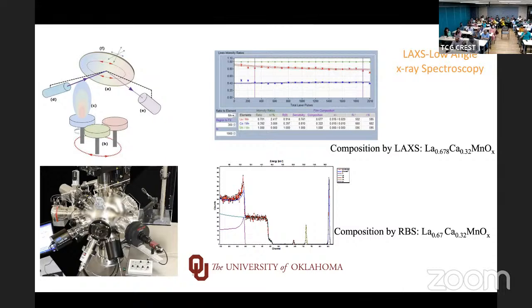Whereas, I send the film to a company outside who do Rutherford backscattering. It's considered kind of a standard for composition measurement, and this data comes back to us after 3 weeks. Look at the composition numbers, 0.67, 0.32. To within 1%, we are able to hit the composition accurately using this technique.